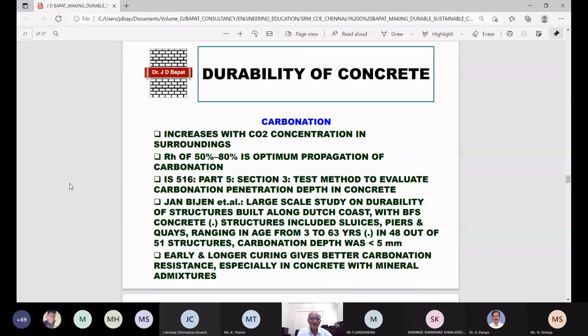Now Jan Bijen is a scientist, and some of his colleagues carried out some experimentation. What they found, large scale study on durability of structures built along the Dutch coast. This was done in the Netherlands with BFS, that is blast furnace slag concrete. Structures included sluices, piers and quays ranging in age from 3 to 63 years. In 48 out of 51 structures, the carbonation depth was less than 5 mm. So people always say that if you use GGBS or blast furnace slag in your cement, the carbonation will be more. So this particular finding of Dr. Jan Bijen has proved that no such thing happens in actual case. Then early and longer curing gives better carbonation resistance. Please remember this, especially in concrete with mineral admixtures.